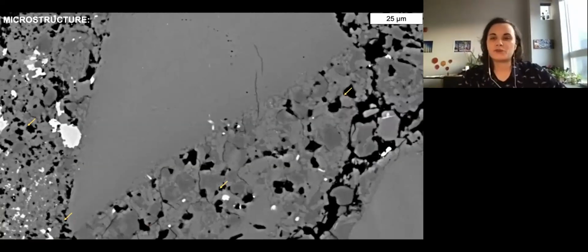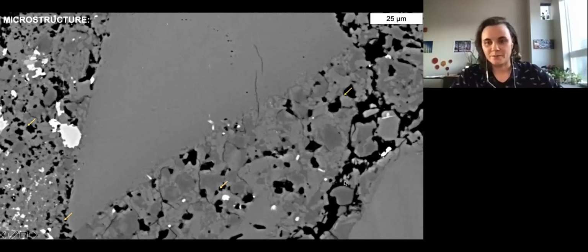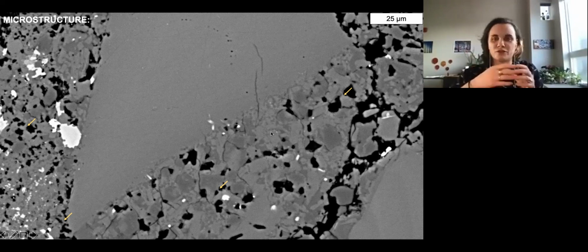In terms of the microstructures that developed, this is what I tended to see. The coalescence of individual crystalline particles to adjacent crystalline particles by the formation of these necks of material. I've highlighted some of them with little yellow arrows, but they're abundant throughout this field of view. And as particles begin to coalesce, they create these patches where the intergranular pore space, shown in black here, becomes very reduced. In some cases, it's essentially eradicated because these patches are so well coalesced.